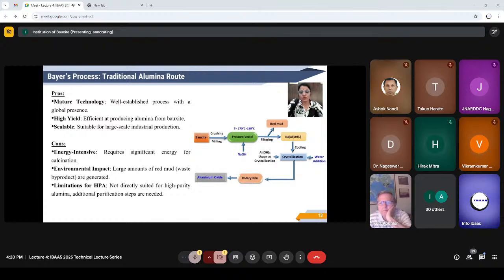And the solution is then cooled and alumina is precipitated out of the solution by seeding it with aluminium hydroxide crystals. This results in crude alumina, which is separated, washed, and then subjected to calcination, where it is heated to high temperature to remove the water and convert it into high purity alumina.